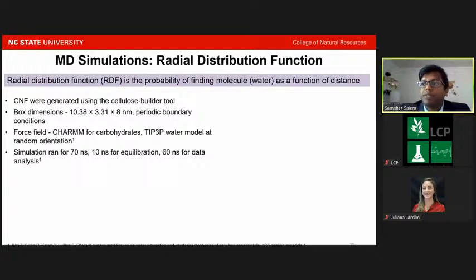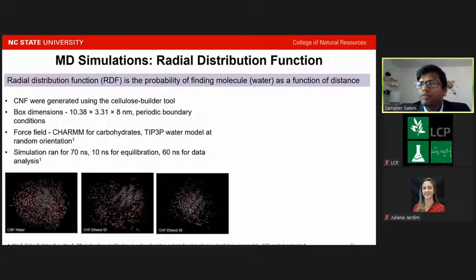After the CNF reached equilibrium, we used Monte Carlo steps. The Monte Carlo steps were added to insert the water molecules at a random orientation. The molecular dynamics steps allowed the movement of the CNF substrate, which results in a more realistic representation of the experimental system. The combined Monte Carlo and molecular dynamics simulation was run for 70 nanoseconds in total, with the first 10 nanoseconds used for the number of water molecules to reach equilibrium, sufficient for water molecules to explore all the possible states of the cellulose surface. And finally, the final 60 nanoseconds was used for data analysis.